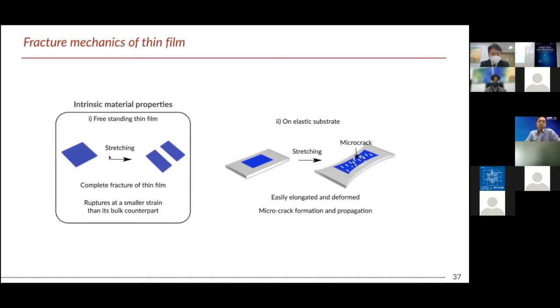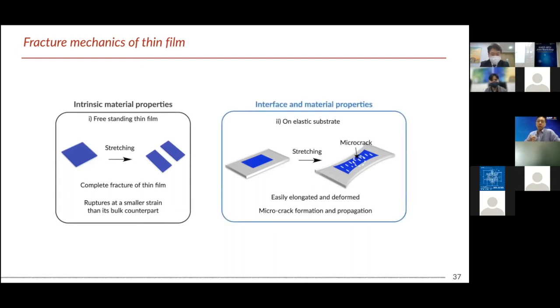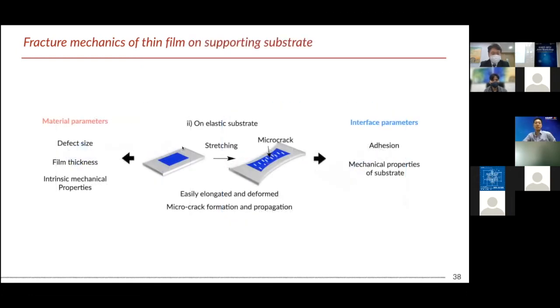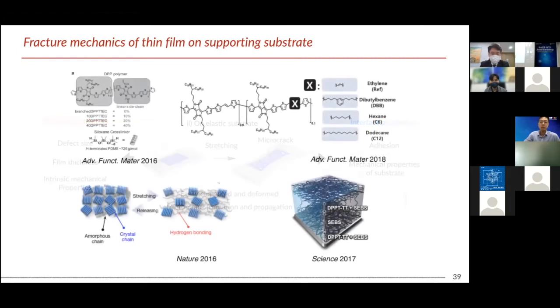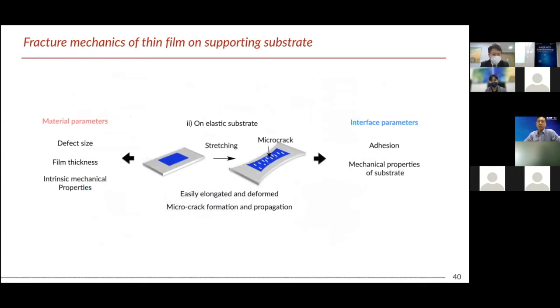In the case of the freestanding situation, it is more related to their intrinsic material properties. However, on the elastic substrate, we need to consider the interface properties as well. So I think in the case of the elastic substrate, we need to consider the material parameter and also the interface parameter. However, most studies so far are more related to material properties engineering. By incorporation of some elastomer matrices, introducing conjugation breakers or hydrogen bonding, or making a nano confinement effect inside the polymer matrix, they dramatically improve the stretchability of the semiconducting materials. However, so far there's no report about how we can engineer the interface and how it can affect the fracture mechanics behavior of semiconducting polymer thin films.